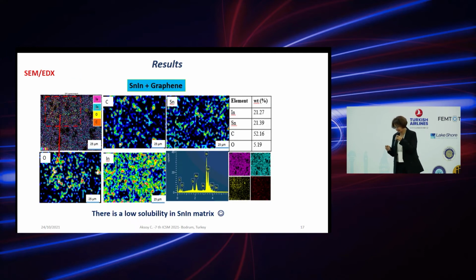And the graphene, we were very curious about this, and we found that it's really difficult to catch the carbon peaks from the EDX maps, but we can see from these maps and these discrete maps, and here the colored elemental maps. The yellow one belongs to oxygen, and the orange one belongs to carbon. We found that its distribution is quite good actually, but maybe we need more time. Maybe a higher temperature can be effective for seeing the dissolution of the graphene in the tin indium system.